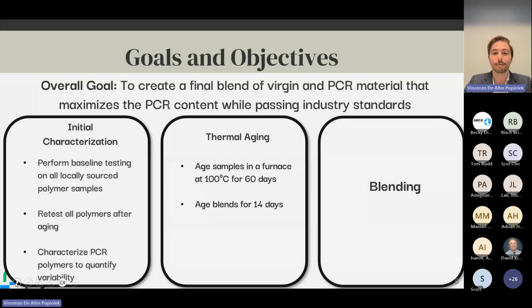Next, for thermal aging, during initial characterization, we aged our samples in a furnace at 100 degrees Celsius for 60 days. This was to simulate a 50-year life cycle out in industry. For our final blends, we then aged these for 14 days. This shortening of time from 60 days to 14 days was due to time constraints. However, that is still twice the industry standard of 7 days.